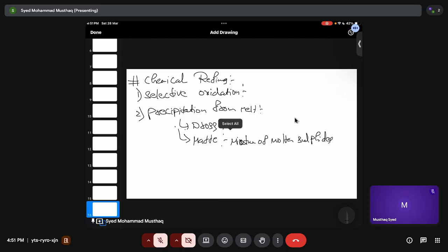And in speiss you find antimonides, bismuthides. But dross is a heterogeneous mixture of solid metal and metal oxide. So it contains both metal and metal oxides, and it is not completely fluid like your matte or slags. It is mostly solid or semi-solid, so the dross that we get is mostly solid, semi-solid, or paste type.